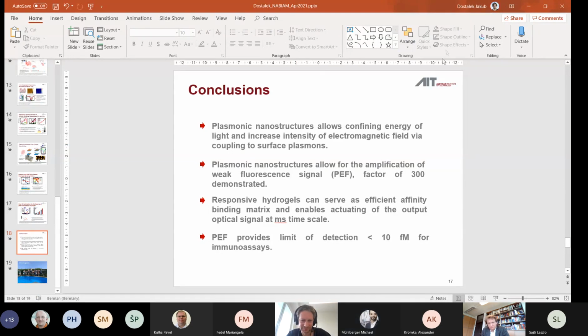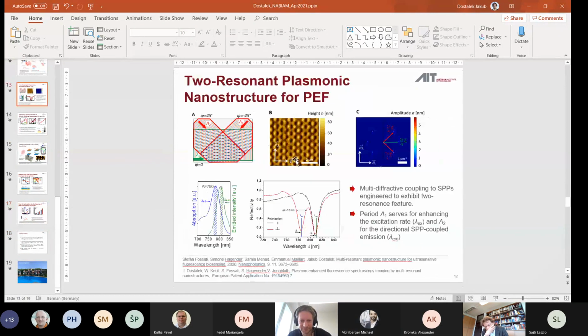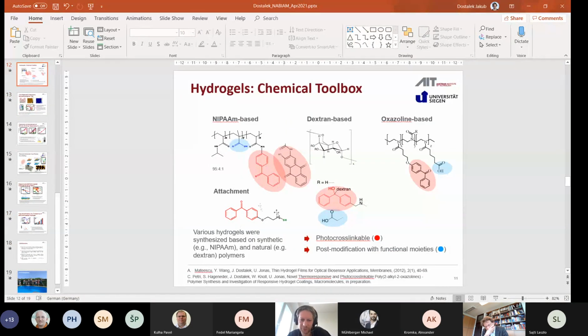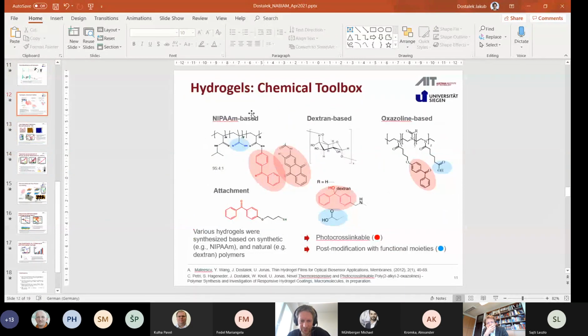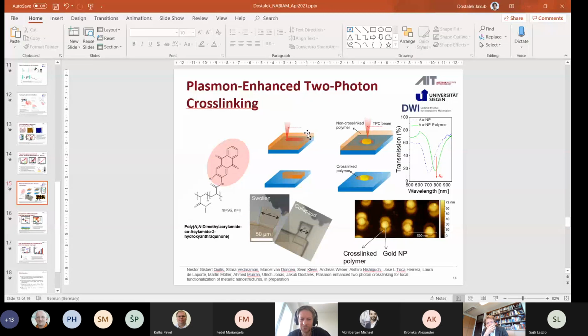Any further questions? I have a short question. Maybe I missed it: the hydrogel you're using, how is it applied to the surface? The gold surface is modified with a thiol having a photoactive benzophenone group, or it can be another group, and then we typically deploy the polymers in the form of layers. We mostly spin coat it, and then we either irradiate the whole layer with UV light, or we use masks to crosslink only part of it. Recently we tried to explore other techniques to locally control where we crosslink the network and at the same time attach it to the gold surface, because of this thiol SAM, which serves as a linker.